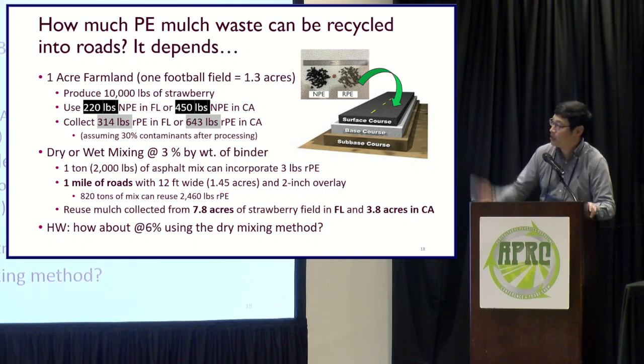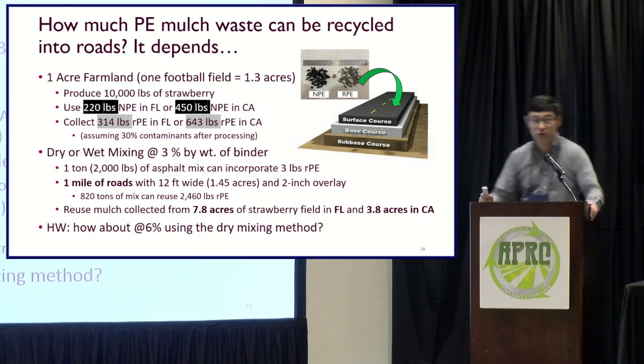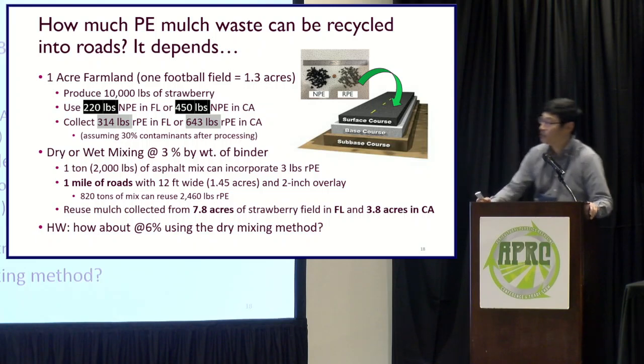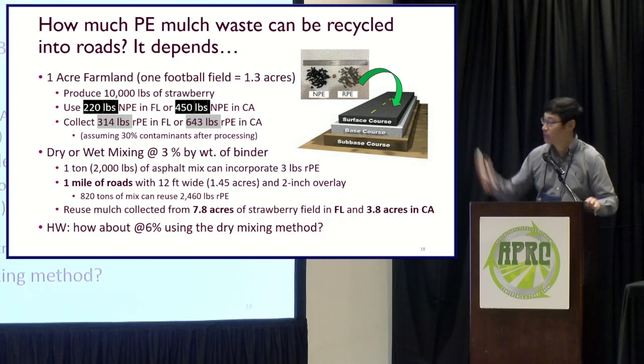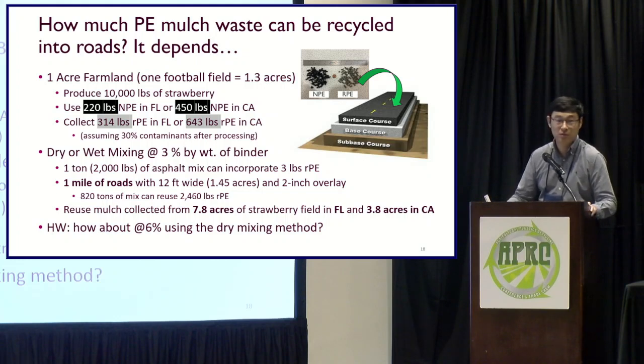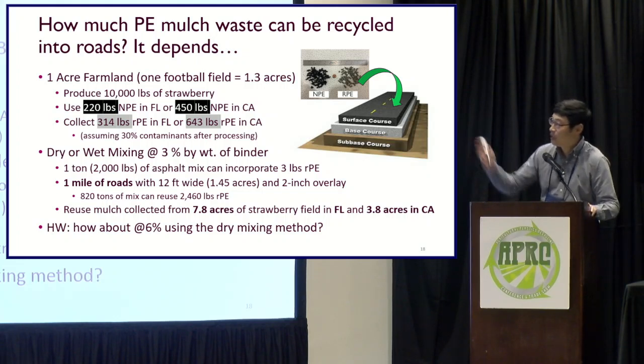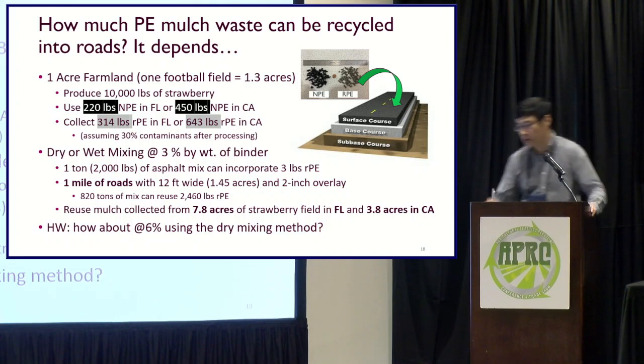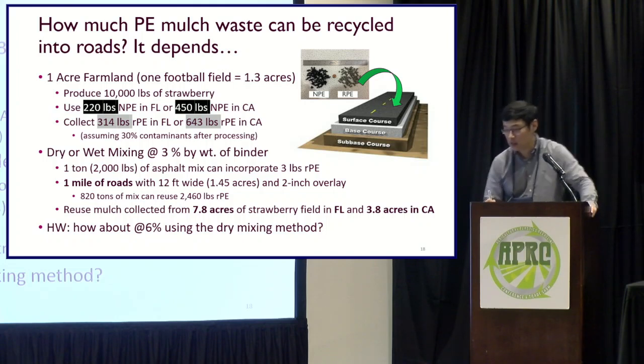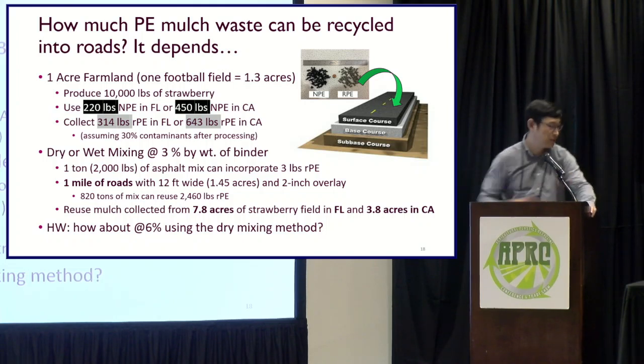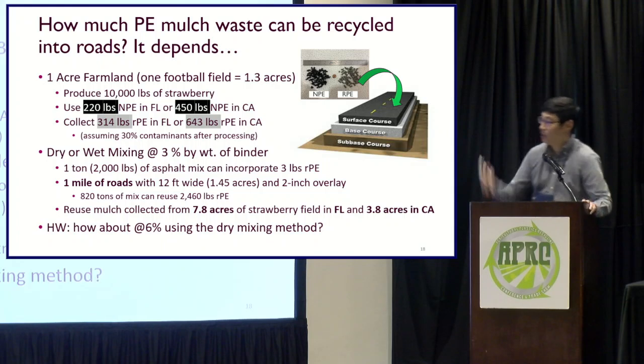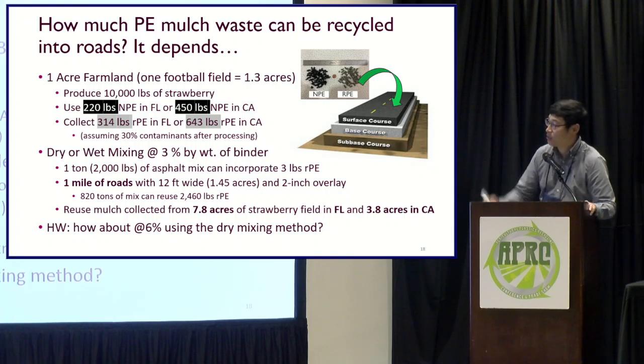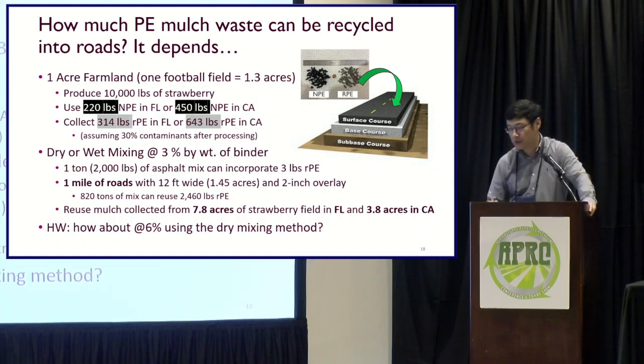Well, in Florida, they use about 220 pounds per acre, and in California, it's more dense, right, using 450 pounds of new mulch. And then when we collect it, we assume 30% contamination after the processing. We can see that data from Karl's presentation. So then we can collect around 300 pounds of recycled PE mulch in Florida and 640 pounds from California.